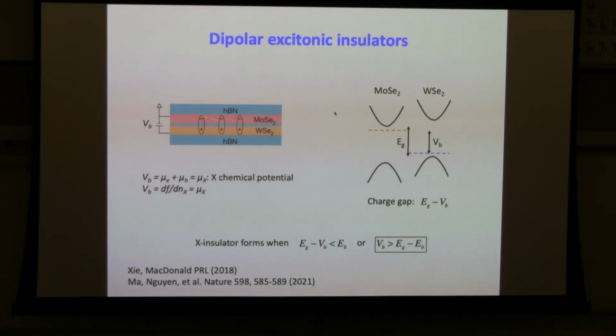But actually, when you are in this state, let's say that your bias voltage is smaller than the Eg, but it's bigger than the exciton energy of the system. In that case, in order to add a charge into the system, it takes a gap. No, I agree there's a charge gap, but that's not the charge gap. That's the neutral excitation gap. Yeah.